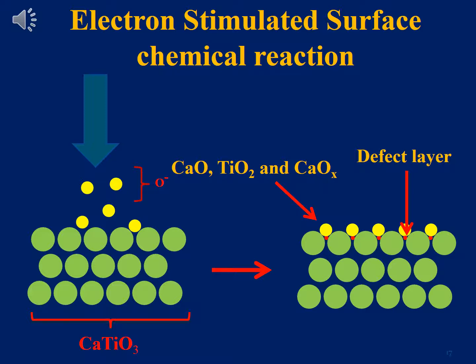Now, as a general remark, if we are going to work with phosphors which will be out in the environment, it is always best to work with a phosphor which is chemically stable. And in our case, we can see that the sample we are working with is not as chemically stable as we would love it to be. For future studies, we will be looking into different ways in which we can improve the chemical stability, or maybe find a coating layer to coat our material in order to prevent the degradation process which may take place in this case.